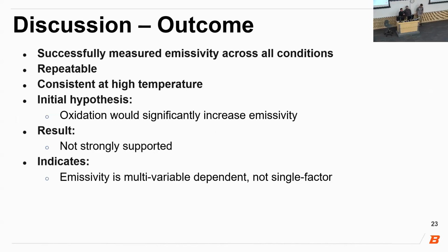Stepping back and evaluating the outcome of the project, we were able to successfully measure emissivity for several grades of graphite through all temperatures and oxidation conditions. The data set is repeatable and shows consistent behavior, especially at high temperatures. Going into the project, the expectation was that oxidation would significantly increase emissivity. Instead, what we see is that emissivity varies, but does not show a strong or consistent correlation with oxidation.